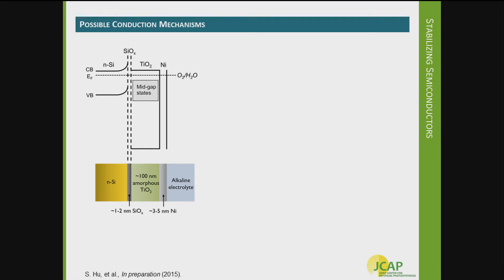There's been work towards understanding the conduction mechanisms in these TiO2 films. In this schematic band diagram, on the left is silicon's conduction and valence band, and in the middle is the TiO2 material with a larger band gap. The initially surprising finding was that photogenerated holes from the silicon valence band are moving through the TiO2, despite the large valence band offset. One option is that mid-gap defect states are acting as charge transport carriers through the film. Another option is a conduction band-type transport mechanism. This is an area of ongoing study within JCAP.